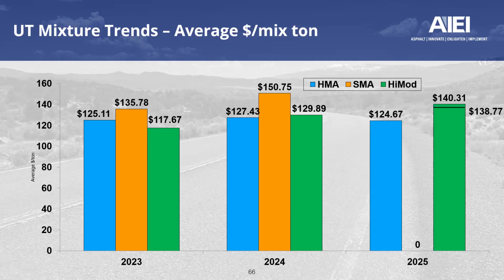You'll also notice in 2025, I show you two different prices per ton for this mix. That is because there was one project that was mixed in the Salt Lake area and had as much as a 6-hour one-way haul to the Four Corners area in the extreme southeastern portion of Utah. And so the two costs that we see there, the 140.31 per ton is all of your highway mixes. The 138.77 is with that additional haul length project, which by the way was 200,000 plus tons being filtered out. So almost a buck and a half savings. A little over a buck and a half savings per ton because of that exceptionally long haul and